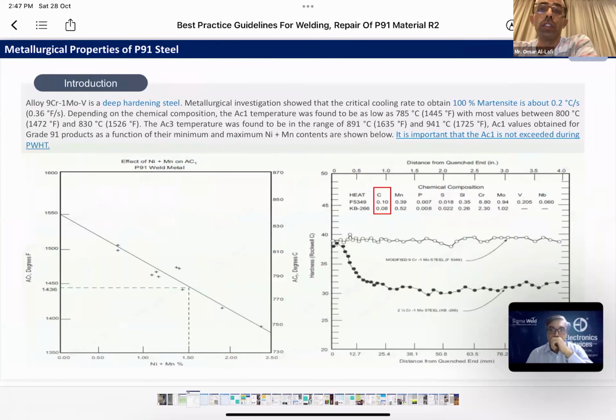The metallurgical properties. So P91 is a deep hardening steel. And what do we mean by that? If you look at the chart on the right bottom, you'll see a Jominy end quench test done in Germany for 2 materials, P22 material and P91 material. Both have almost the same carbon content, but the hardenability of P91 is much higher than P22 material. This is in part because of the martensitic formation during cooling. That martensitic structure in P91 will give higher strength and higher hardness in the steel.